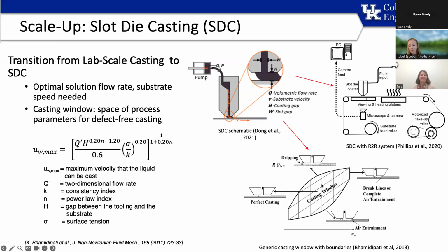And this casting window is where we have perfect casting, where we're going to be able to develop a membrane that has homogeneous properties throughout the membrane, where every single piece of the membrane will provide the exact same permeability and rejection. When we are outside in this area where potentially the flow rate of the dope solution coming out is too high, there's going to be an accumulation back here of the dope solution, and it's called dripping.